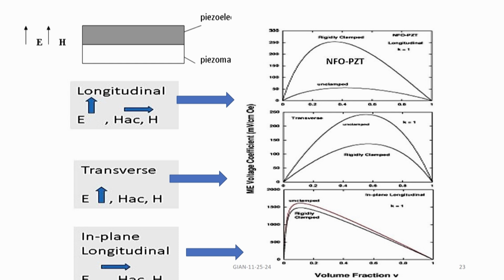So, when the composite has equal volume of nickel ferrite and PZT, that is when the response of the sample is maximum. And also you see here that rigidly clamped and free unclamped samples, they have different response to an applied magnetic field. And these are in plane magnetic fields. This one is magnetic fields perpendicular to the plane, and this one is in plane longitudinal. The PZT is poled in this direction, all the magnetic fields are also in this direction. You measure the voltage across this direction. Okay. And I haven't seen any experiment for this particular geometry.